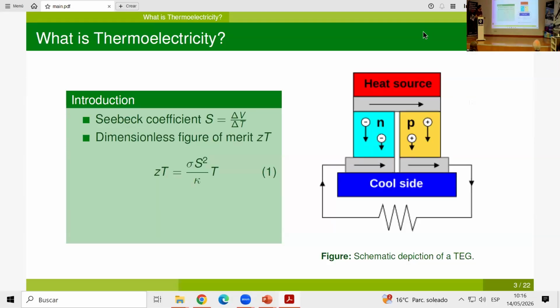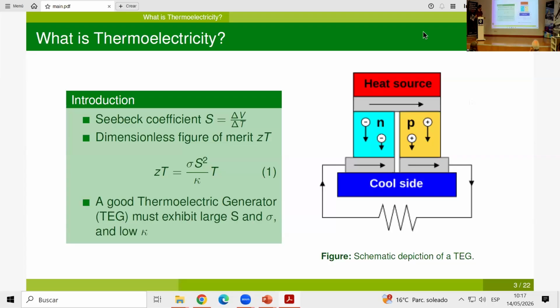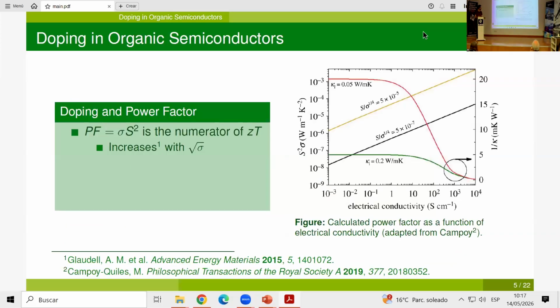And we measure the efficiency of thermoelectric generators with this dimensionless figure of merit, ZT, where we have the electrical conductivity, the Seebeck coefficient squared, temperature, and the heat conduction, the thermal conductivity, K. So a good thermoelectric generator must exhibit large S and electrical conductivity, and low K. So about doping in organic semiconductors, we call the numerator of the ZT the power factor. It increases with the square root of the electrical conductivity and not linearly because the Seebeck coefficient is also affected by the electrical conductivity negatively, unfortunately.